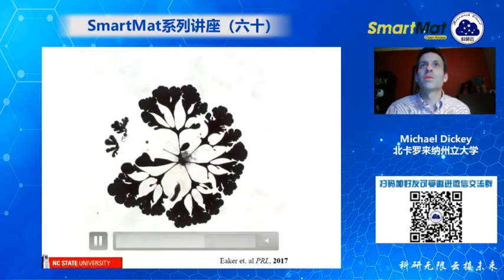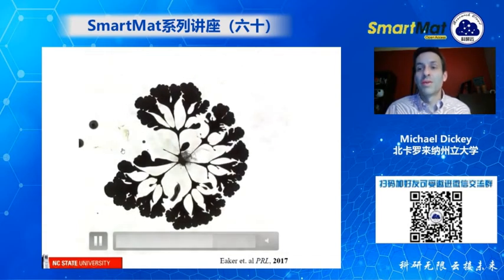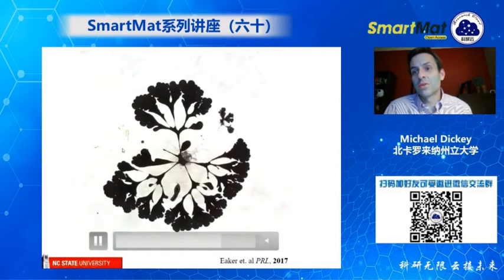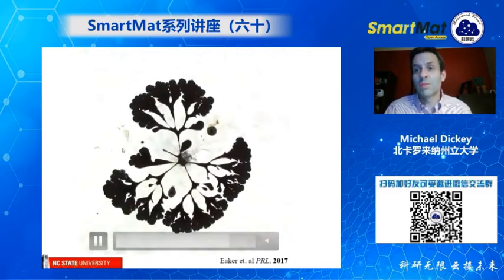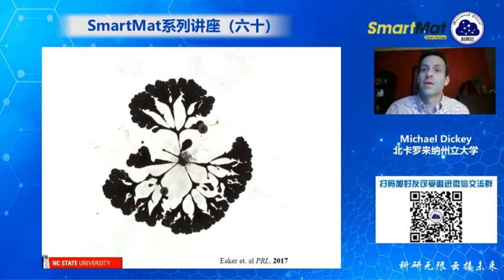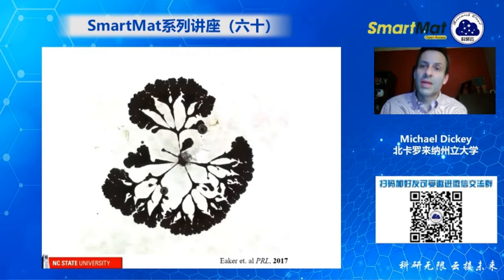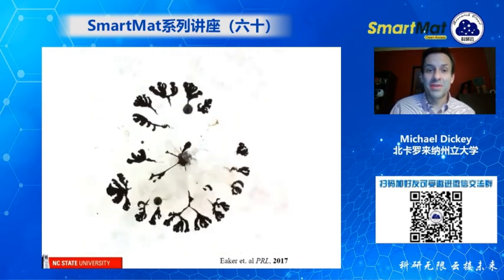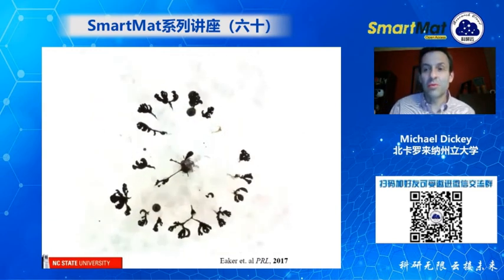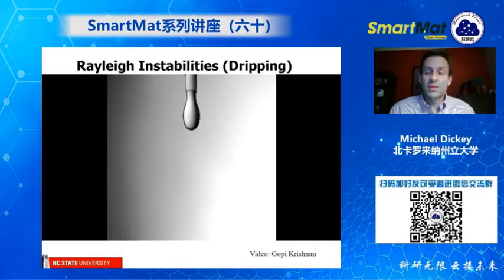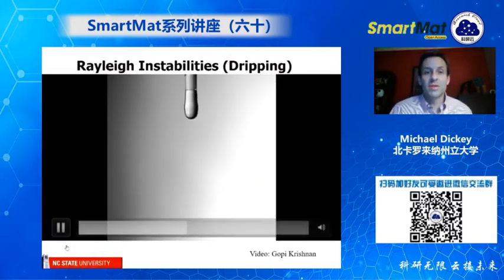And you can see that it typically will break up, because if it's not connected to the electrode, it's not getting the electrochemical reactions that drive this process. So again, I'm sorry I don't have time to tell you all the details. I hope this just gets you interested to learn more. But basically what we think is that the surface oxidation, electrochemical oxidation, deposits species on the surface that help lower the surface tension. So more recently, we use this to deal with what's called Rayleigh instabilities.